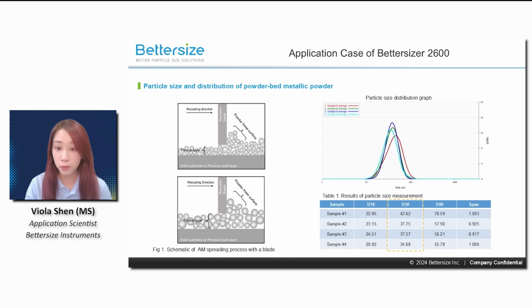Let's dig deeper with PIC-1, the image analysis module. With the combination of PIC-1, more than 20,000 particles from these 4 metallic powder samples were measured in time. The figure 2 on the left side presents images of individual particles from 4 test powders captured during the shape evaluation. Table 2 provides the circularity of all samples, calculated by the Bettersize software.